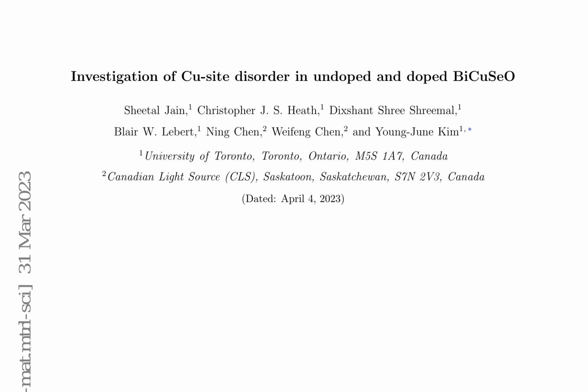The lack of significant temperature dependence in the extended X-ray absorption fine structure (EXAFS) data across both samples indicates that the mean square displacement of the Ag dopant does not change significantly in the temperature range studied, from room temperature, 298 K, down to base temperature, 78 K. This behavior is similar to that of Cu, as observed in XRD data shown in Figure 3b.